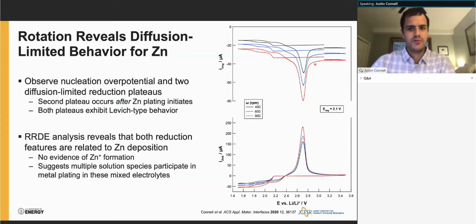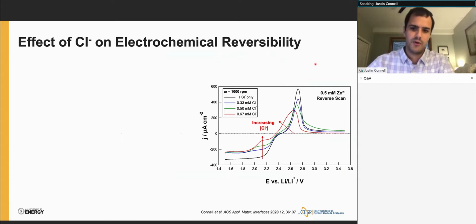And so to understand what's driving this behavior, we can start playing around with the solution composition. What I'm showing here in this scan is focusing only on the reverse scan, where deposition ceases, more or less corresponding to the thermodynamic potential for metal deposition.